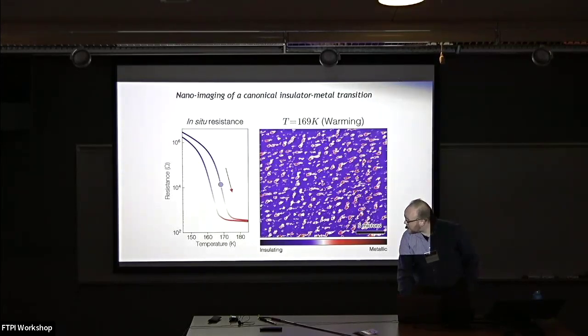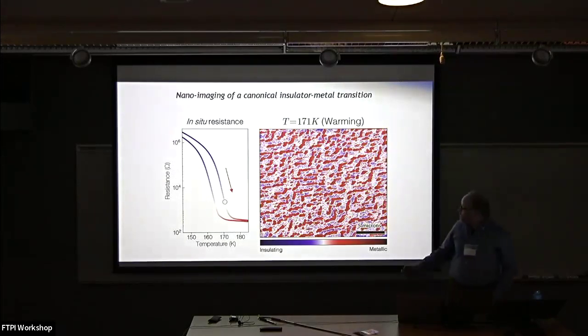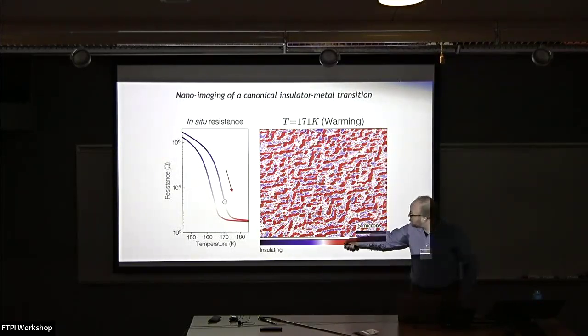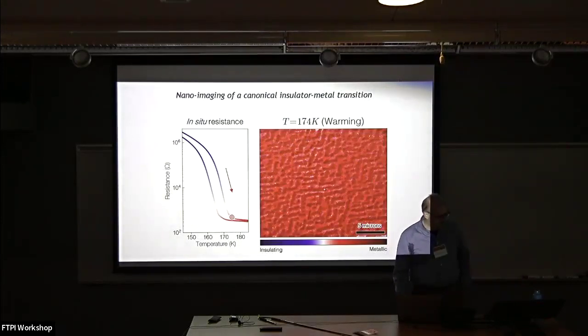And you'll see it's not exactly the same movie that we're playing in reverse when we heat the fellow up. We nucleate the metallic phase. We have a percolation and growth of the metallic phase. We finally bypass also the inflection point in the resistive transition, as we would expect to do.